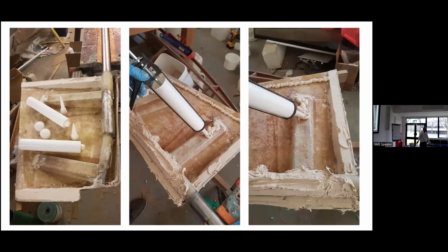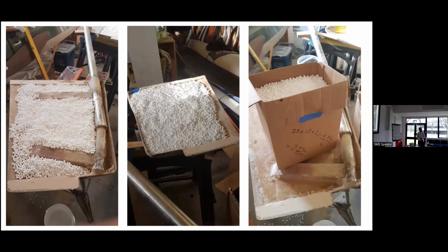So I chose to go down a different route, and I glued it together with a combination of one of our lightweight fillers and G-Flex, which you see on the next slide. So I put this in a caulking gun and glued it together. Then I filled it with an epoxy foam.